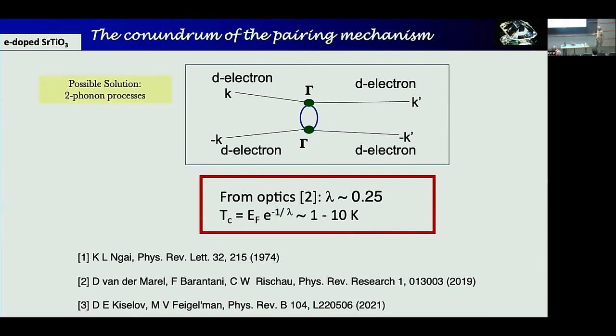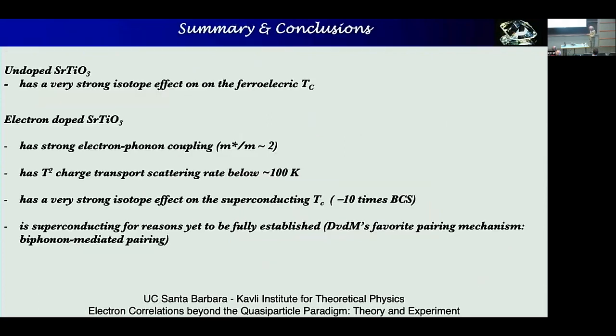This was also followed up by Kiselov and Feigelman, who made more detailed predictions about superconductivity. So it is a possibility. And since there is really no good other candidate, it's a reasonable candidate. So that brings me to the summary. Undoped strontium titanate has a very strong isotope effect on the ferroelectric Tc.